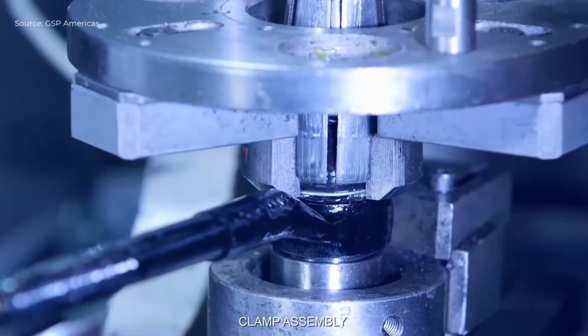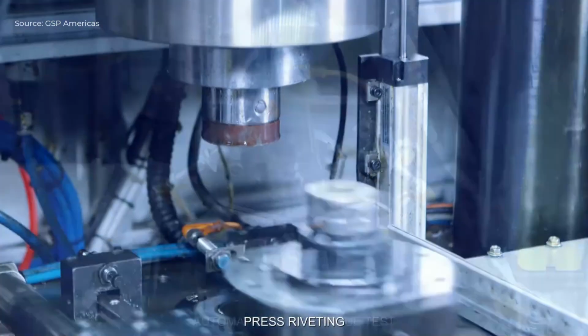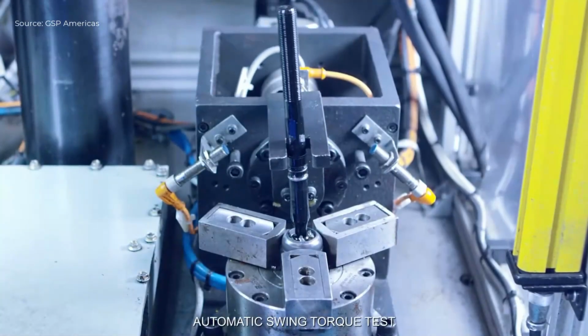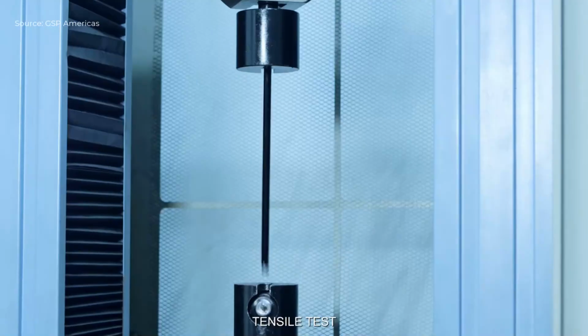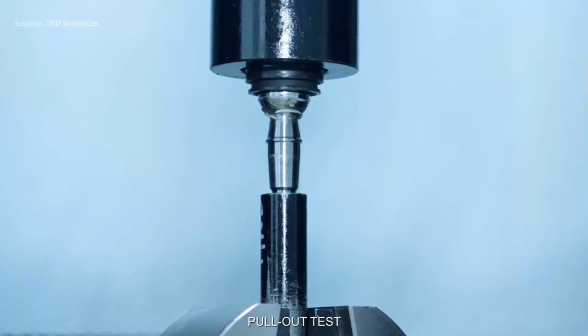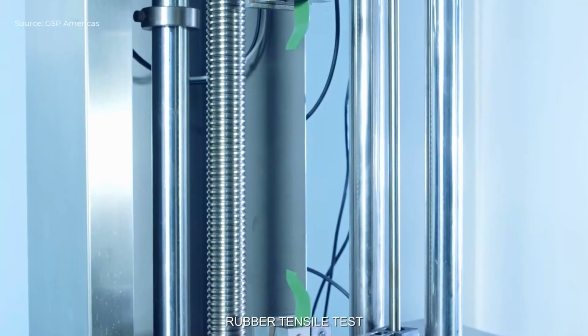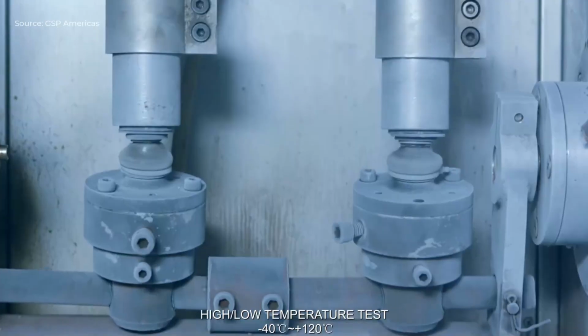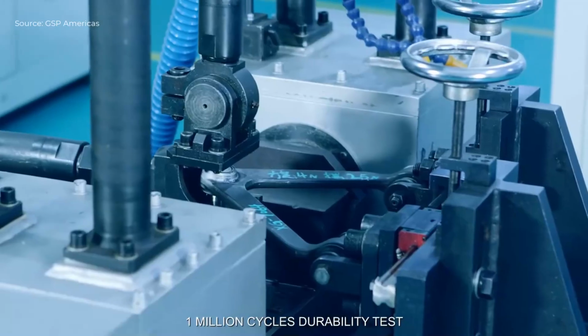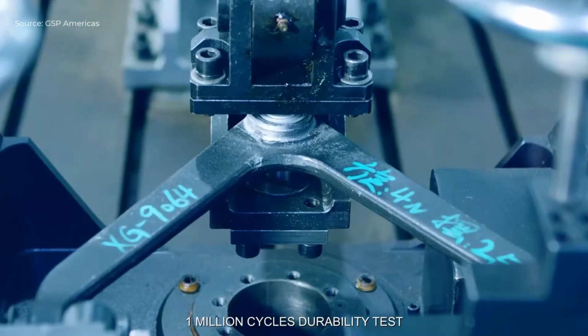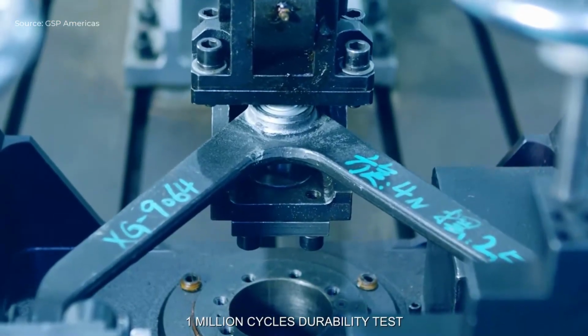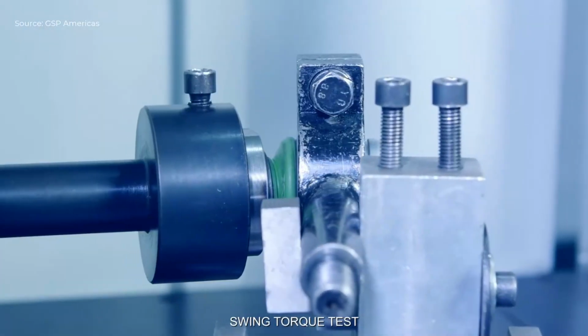Comprehensive quality control includes roundness, hardness, tensile, and pull-out tests, along with rubber tensile and durability tests for ball joints. Environmental testing ranges from -40 degrees Celsius to +120 degrees Celsius with up to 1 million cycles. Finally, salt spray testing and final inspections are conducted before parts are stored or dispatched from the GSP Logistics Center.